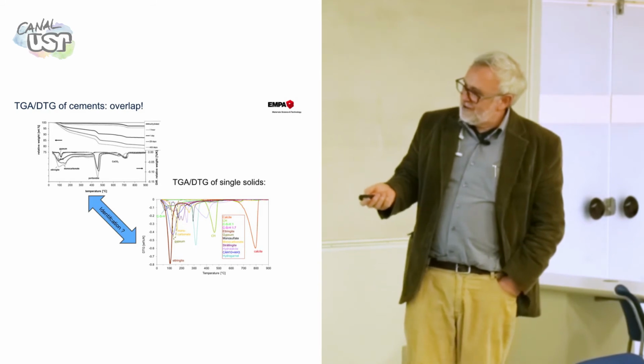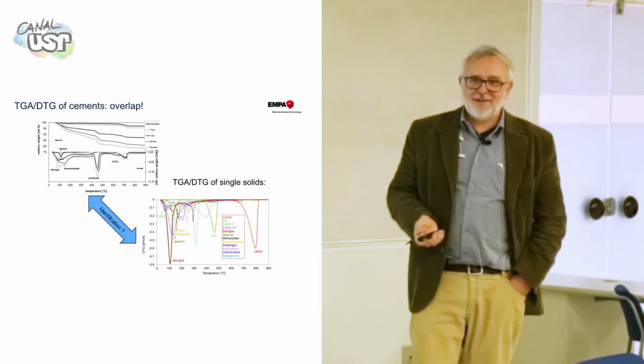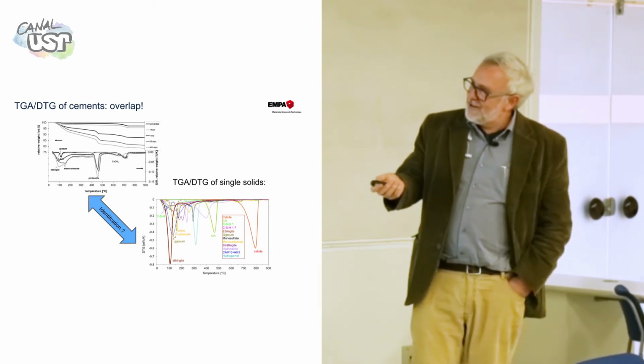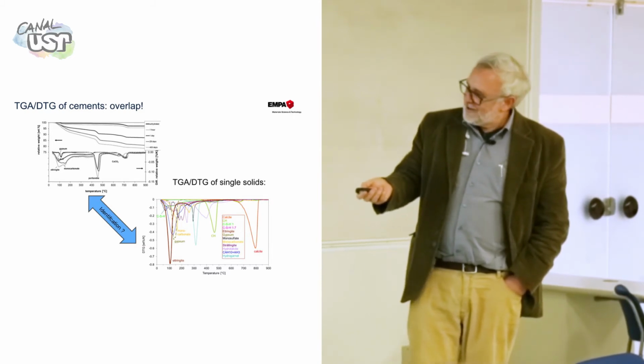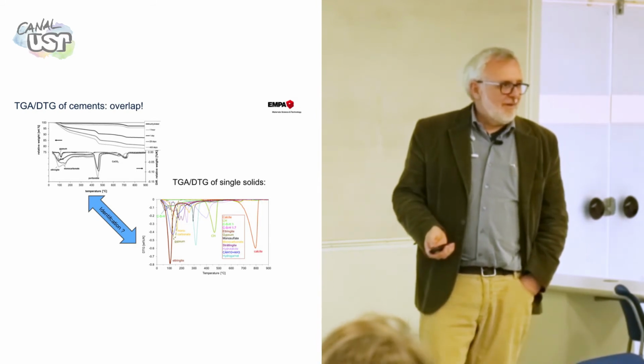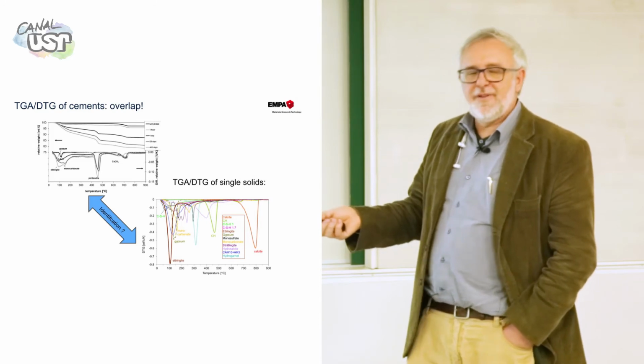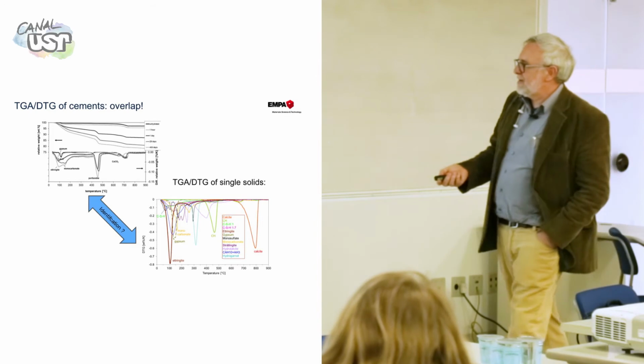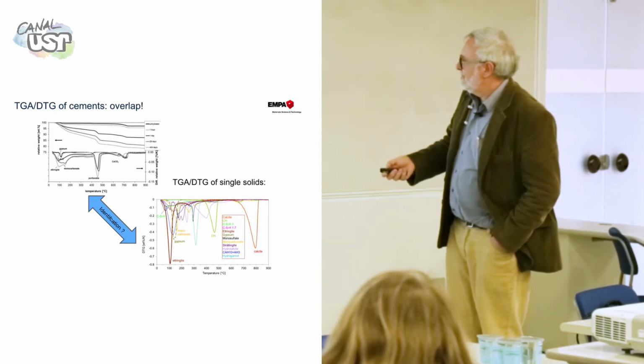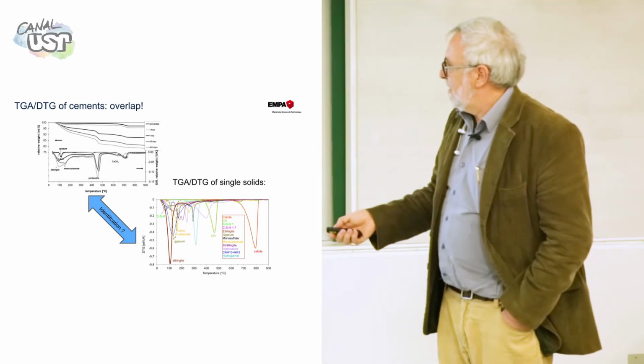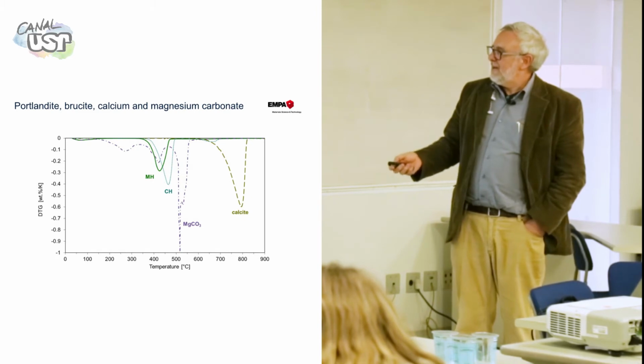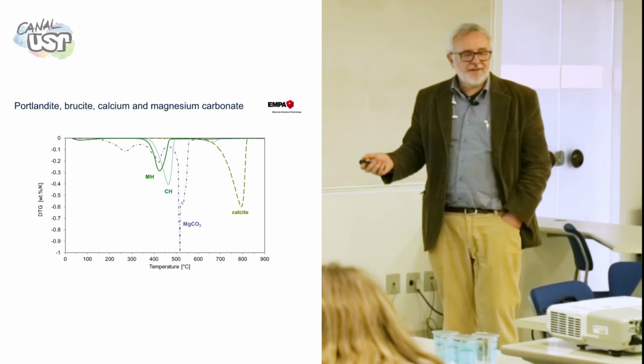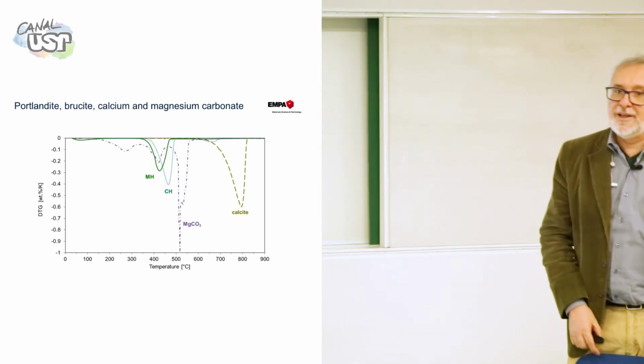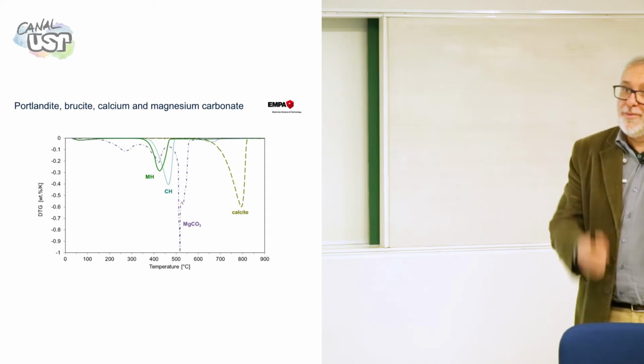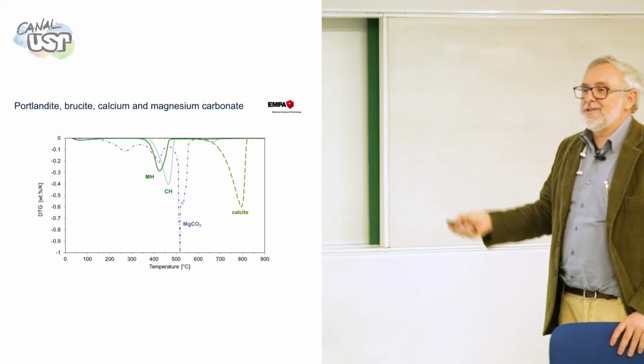These are TGAs, DTGs, from pure phases that are present in cement. What we see is like that, but these are the result of the sum of these different curves. So what you measure at every moment is a combination of different things. And well, it's CSH, ettringite is here, gypsum, this is calcite, this is pure portlandite, and so on. Here you have brucite, magnesium hydroxide, and this is magnesium carbonate, and this is calcite. Most of the fillers that people are putting in cement nowadays have magnesium, some of them dolomitic. So this peak is going to be close to calcite here.